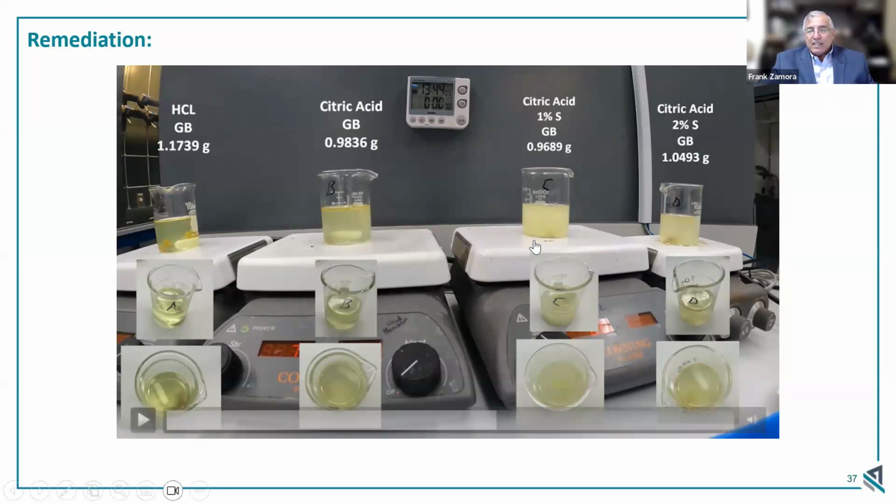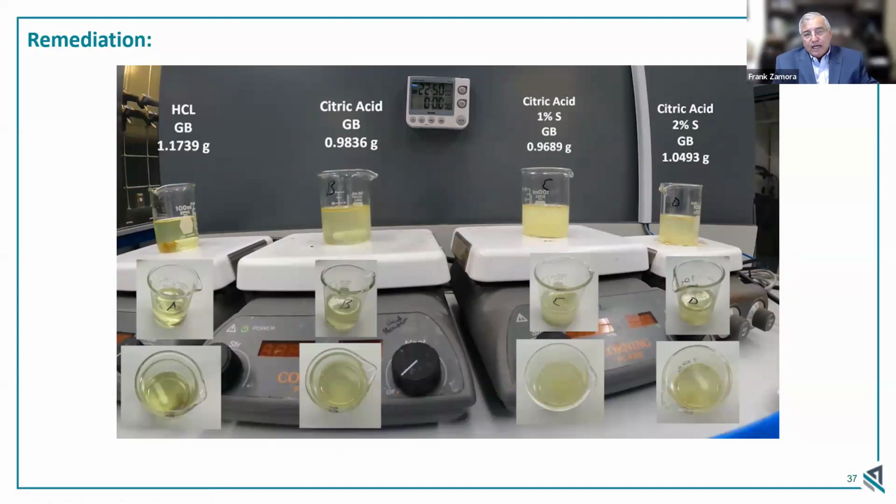So at 1%, it seemed to be the optimum. What we're looking at here from the top is the oil sheen, which has basically parked itself around the rim of the beaker, versus one that is actually dispersed across the entire fluid. So as we go through a 24-hour period, we're able to basically say the citric acid in this particular sample worked very well in dispersing the polymer back into solution to help remove it from your wellbore.